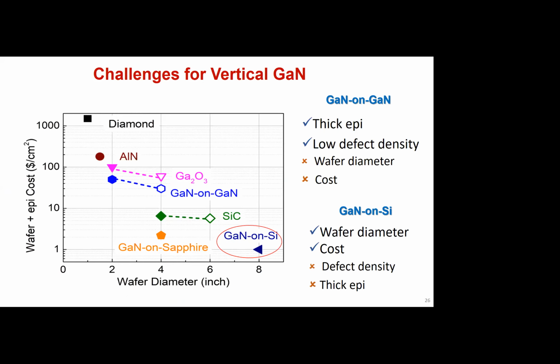So yeah, everyone wants to make semiconductor devices in silicon because we have existing foundry facility and a $1 billion industry there. So if anything we can make on silicon, that would be cheap, scalable, and ready to commercialize. But I think you already kind of answered the question. First, it's very difficult to avoid defects when we're trying to grow material on a different substrate. For example, if you try to grow gallium nitride on silicon, it's very difficult to avoid defects because of the difference in the lattice parameter and the difference of the coefficient of thermal expansion, which also creates a problem with thermal management.